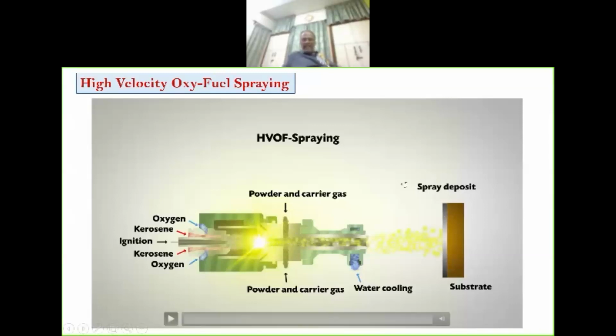So we can get a very dense coating here. Of course, time of flight is low, so we cannot melt high melting point solids like oxides. It's good for metals. It is good for carbides, where we have a thin layer of metal covering the carbide particles. It's possible that way. It's well known. It's a commercial success story.